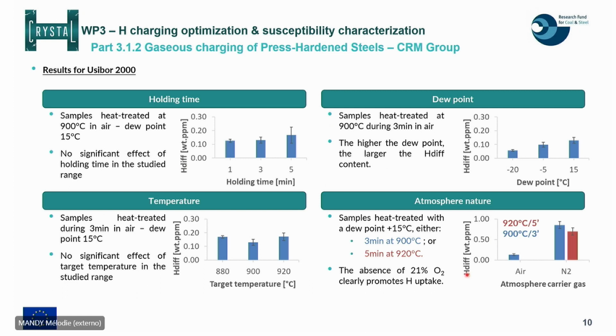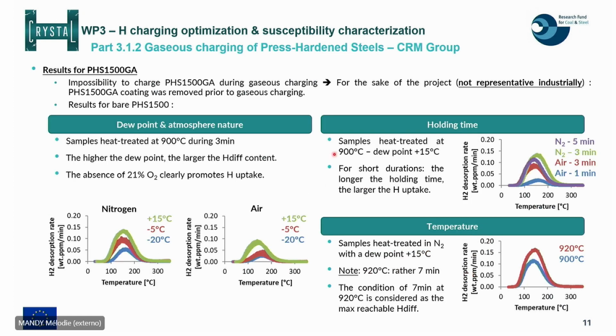So that was for Usibor 2000. The same work was performed for PHS 1500. It was a bit different in this case because we had encountered many difficulties to charge these materials with this zinc coating. So in the end, for the sake of this project, we were forced to charge this material by removing firstly its coating. So the result that you see here is not about PHS 1500 GA, but bare PHS 1500.